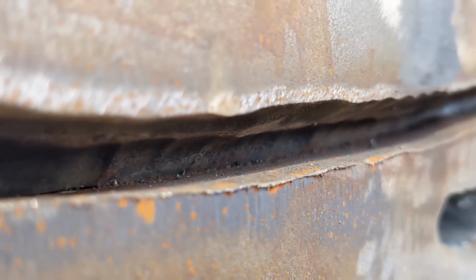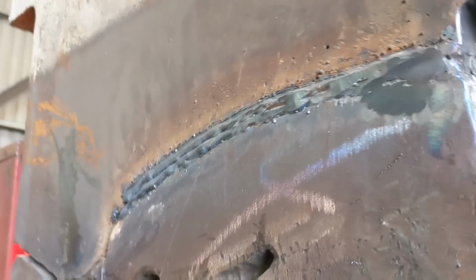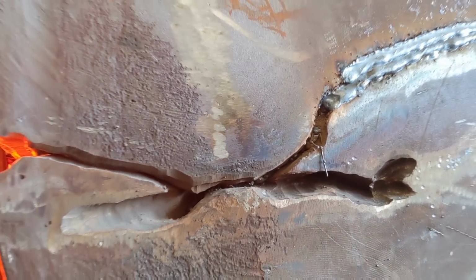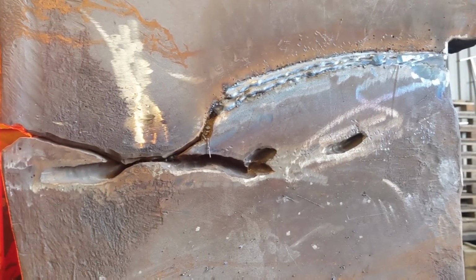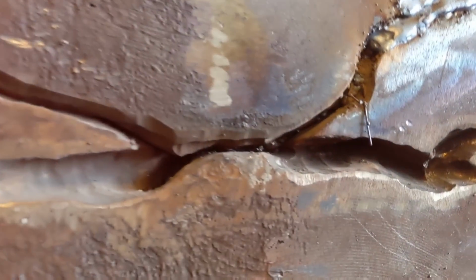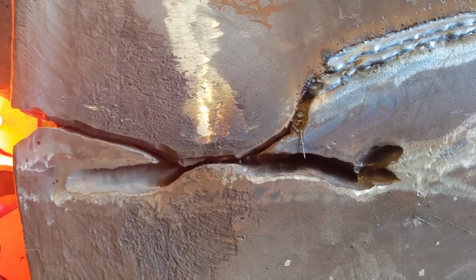So next we're going to start on the very outside welds on each side of the jaw. You can see into the bottom of the root there is absolutely lovely, in that nice straight run. However, the far side is a much bigger mess. We have multiple cracks in various different places and messy junctions. All of the root welds that you can see in there will be back gouged into perfectly clean weld, eliminating all flaws and any little issues with that root weld on the inside. I usually consider the root weld a write-off anyway, with the intention of gouging it out completely.